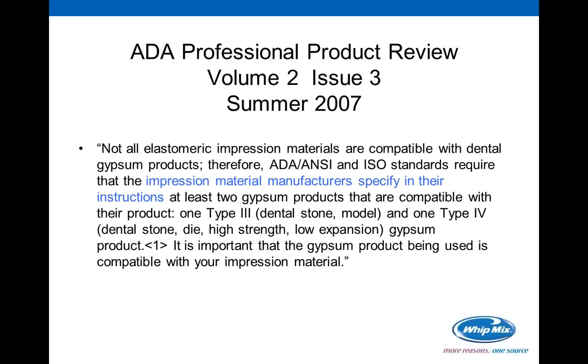Generally, that's one type 3 stone, which is model stone, the yellow stone that we're talking about, and one type 4, or a dental stone, die stone, high strength, low expansion gypsum product. It's important that the gypsum product you use is compatible with your impression material. When they talk about compatibility, they're talking about the fact that the gypsum will reproduce what the impression material produces. We're not talking about compatibility chemically. There aren't any compatibility issues chemically that are going on there.